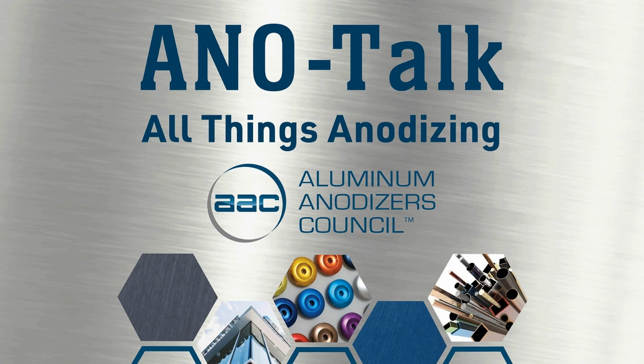Instead of me just continuing, ask Mark. No, I'm curious. With pulse, are you going to need more volts to drive the amps as your coating thickness gets thicker? The voltage depends mostly on the thickness of the coating, because the thickness of the coating is the resistance of the coating. Yep. Ohm's law: the resistance is as it is, no matter if you have done pulse anodizing or direct or AC. So the voltage should be the same.